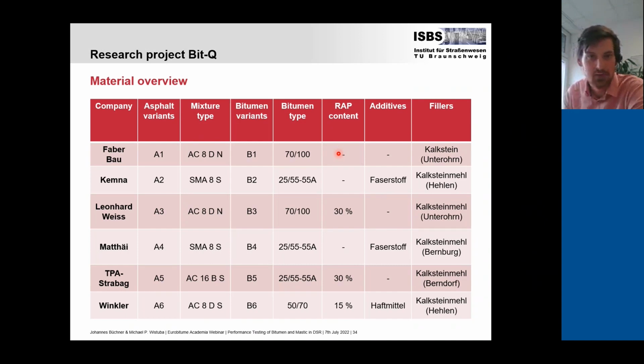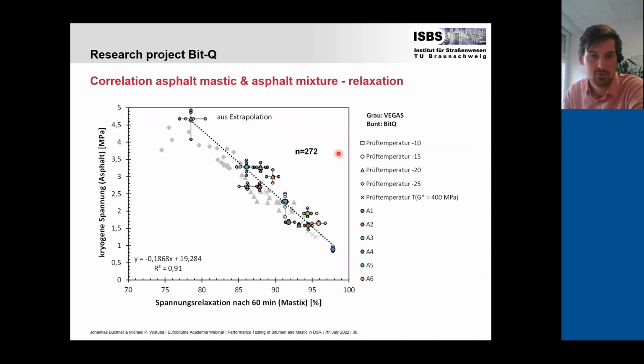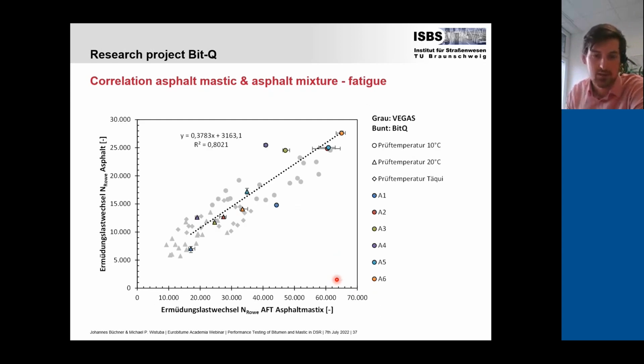So this was kind of the worst case for fatigue, but it's good for the low temperature behavior. You can see here in the low temperature relaxation that it has a relaxation capability at -10 degrees, I have to check, the circle is -15, of 98%. So almost all stresses can be relaxed by the soft binders, but we don't have such a high resistance to fatigue cracking, as you can see here with very low load cycles. We can also see the stiffer materials and more advanced materials, which have higher resistance to fatigue. Here at the top, we had the second test temperature, which was 10 degrees C.